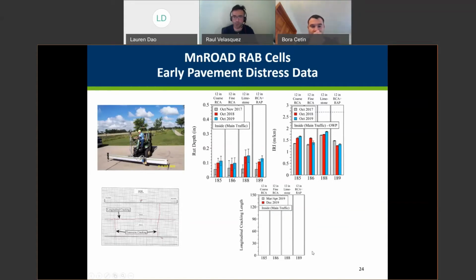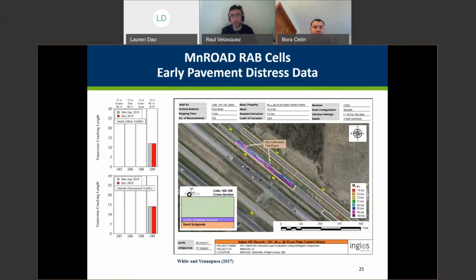Longitudinal cracking was not observed for the first 2 years. Here's some nice survey from Mike and people at MnROAD. Thank you for doing all this work. And an interesting observation we got is in terms of transverse cracking. Early on, after 2 years of material being in there, we have some transverse cracking observed in cell 189, which is the one with a mix of RCA and RAP. No transverse crack measured for the other cells.